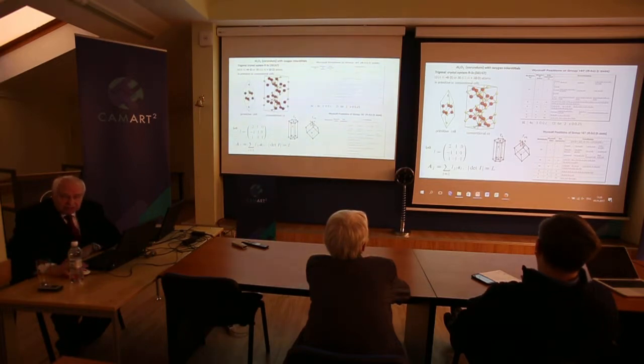So don't forget that for a structure it's necessary to give it. And oxygen occupies the 6E position with local symmetry only C2, or simple rotation by 180 degrees, and again 1 parameter in the Wyckoff position. So this is the primitive unit cell.